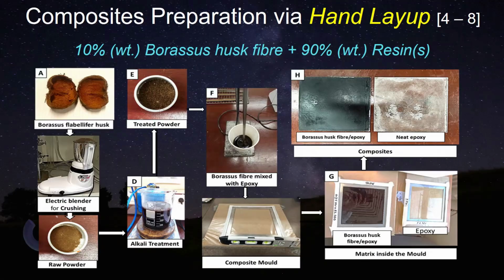We put all the mixture into the mold. We keep those molds in the normal atmospheric condition for 1 day, and then we take out the mold and put it into the oven at a specified temperature for curing. Depending on the resin, this curing method is different, and that is adhered to by the technical data sheet provided by the supplier.